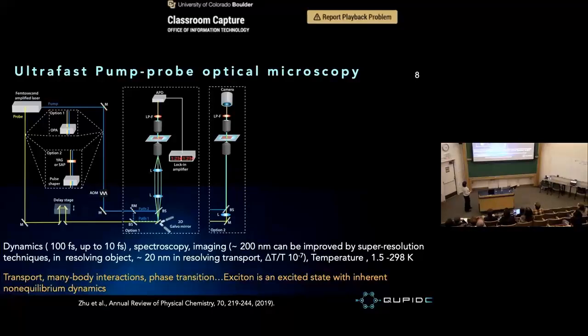And two is that in this solid-state system, the distance between excitons is much shorter. They are not half a micron apart, again because we wanted to induce stronger interaction. What that means is that it's harder to get single-exciton spatial resolution. Right now, our spatial resolution is on the orders of 200 nanometers, which is still a collection of excitons. It's not a single exciton, as I would explain. But I will try to convince you that even with that caveat, we can still track where these excitons are collectively and understand their phases.